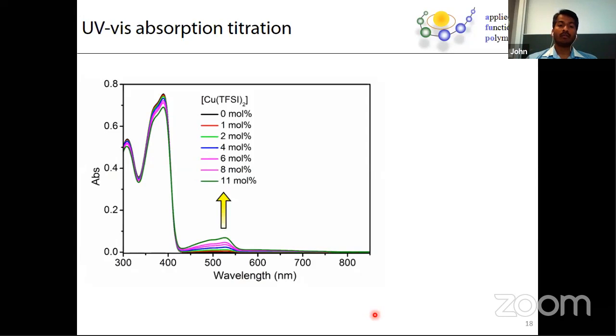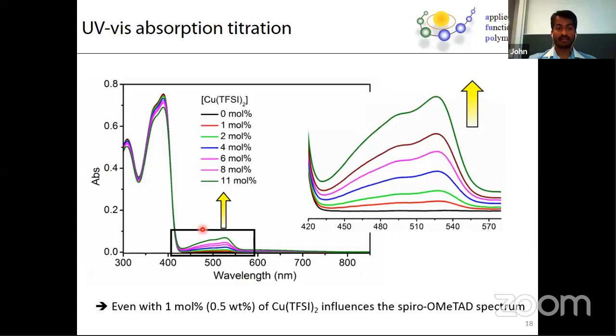While we keep on increasing the dopant concentration, we start to see new features at around 520 nanometer, which you could see much better in here. On the other hand, this is how pure spiro would look without any feature in here, which you can now correlate with the spectroelectrochemistry data. With increasing copper TFSI concentration in the spiro-OMeTAD solution, you start to see a new peak that is increasing in intensity with respect to the copper TFSI concentration. And the important factor here is that even with 1 mole%, the red curve, we are able to see the new peak in the spiro absorption.